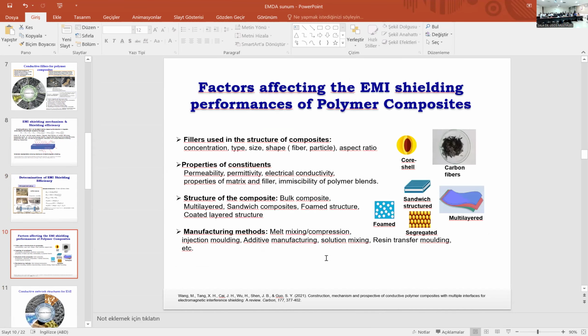Many factors affect the EMI shielding performance of polymer materials. These are mainly the filler type, size, shape, and aspect ratio; the properties of the constituents, such as permeability, permittivity, and electric conductivity of the matrix and filler materials; the structure of the composite, such as bulk composite, multi-layered, sandwich structure, and foam structure; and the manufacturing methods, such as melt mixing, compression and injection molding, additive manufacturing, and solution mixing.